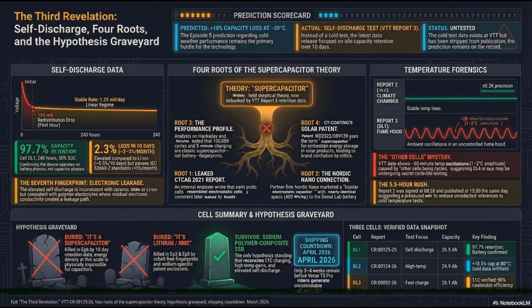The first thing that jumps out to me when looking at that summary is the capacity spread. Yeah, the cells range from 24.9 amp hours on the low end to 26.7 amp hours on the high end. That is a massive 7.2% variance across visually identical prototype cells manufactured on the same line. That tells you that while their screen printing manufacturing process is incredibly impressive, it still suffers from severe prototype-level tolerance and consistency issues. The manufacturing consistency is clearly still a work in progress.